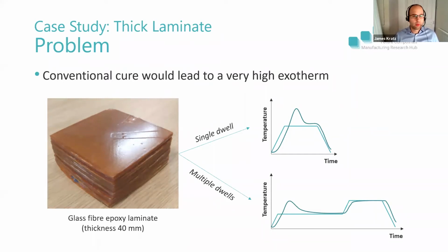So if we're trying to make a thick composite laminate, conventional curing tends to lead to a very high exotherm. If you think about a single dwell process for a thick laminate, you tend to have a really significant overshoot in temperature just due to the curing of the polymer and the low thermal conductivity of the matrix. One of the common ways to alleviate this problem is to increase the length of the process cycle. You can either add multiple dwells, slow the ramp rates down. There's even the possibility of a thermal cooling. So all of these things then tend to increase the time.